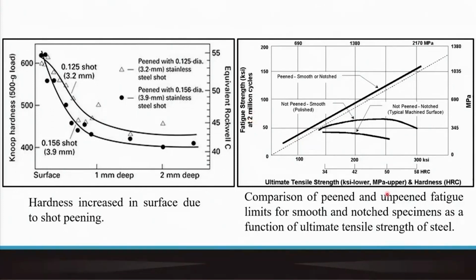So having shot peening obviously is much more beneficial than the cases when the material is not peened and notched. In such a case it will fail much earlier, and not peened with yet a smooth surface can show slightly higher strength, but the maximum amount of fatigue strength you can see is when the material is not only subjected to shot peening but is also smooth.